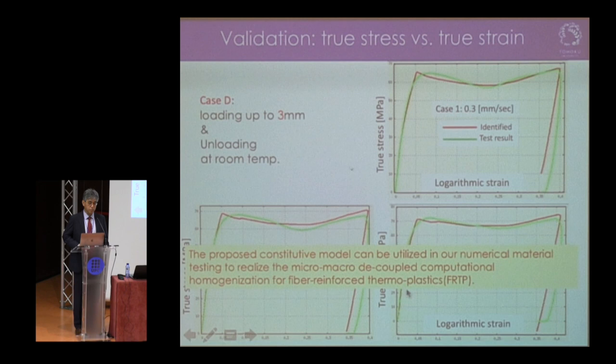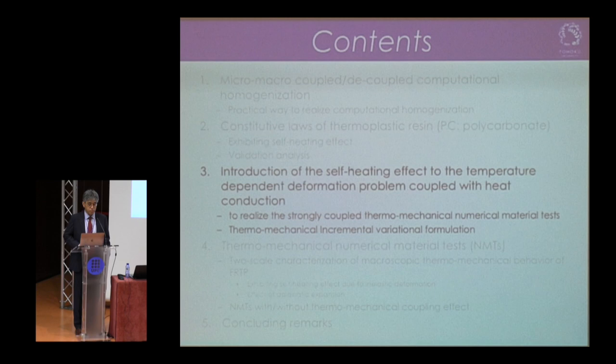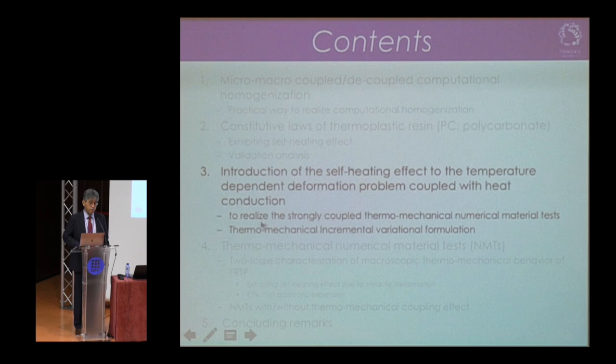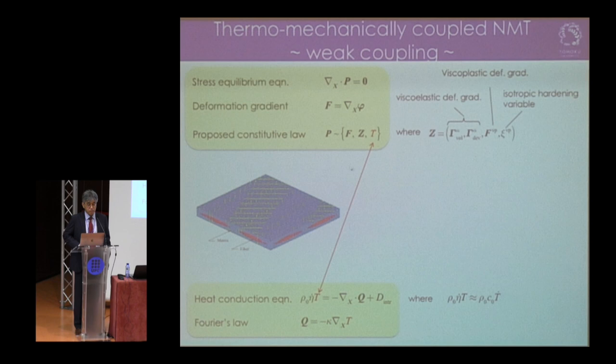At this stage, we have considered neither heat conduction nor heat generation. So the next step is to introduce the self-heating effect into the temperature-dependent deformation problem coupled with heat conduction, in order to realize strongly coupled thermomechanical numerical material tests. For that purpose, we employ a thermomechanical incremental variational formulation for the strong coupling problem. Let me briefly describe the standard weak coupling scheme and then the incremental variational approach.